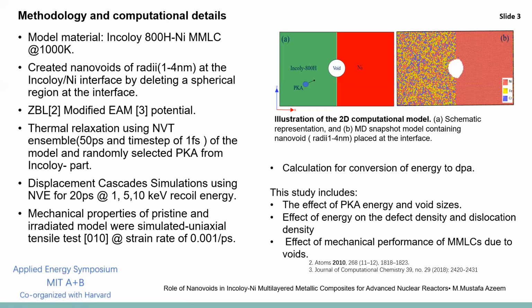for different void sizes of radii 1 to 4 by selection of different dpa, displacement per atom, which is determined through the SRIM code. The selection of the PKA is chosen from the Incoloy part, and the PKA is randomly selected such that each constituent element is represented, irrespective of their mass. The velocities of incident particles are around 99% in the direction normal to the nickel interface.